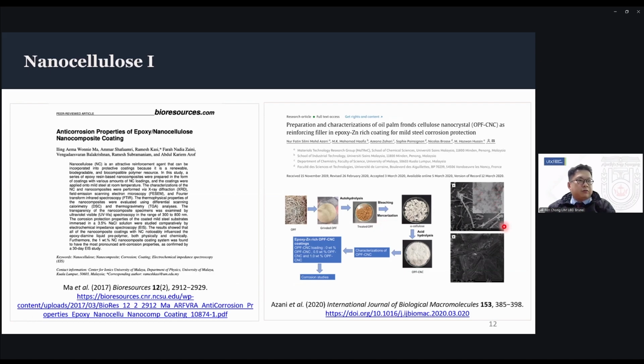On the left was one of the first reported deployments of nanocellulose used in epoxy coating. The nanocellulose was synthesized from microcrystalline cellulose using acid hydrolysis, specifically sulfuric acid hydrolysis.